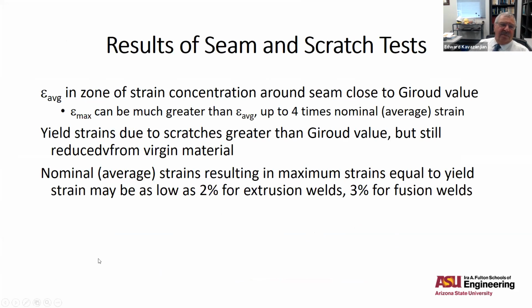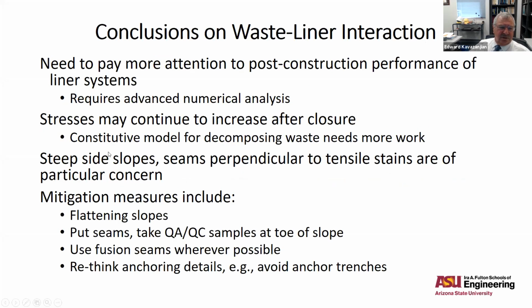So we concluded from these seam and scratch test results that the average strain in a zone of strain concentration around a seam is close to the Giroud value, but there's a maximum tensile strain that can be much greater than the average, up to four times the nominal or average tensile strain in the geomembrane. And, you know, geomembranes are pretty brittle materials. Once you start a tear, the entire geomembrane tends to unzip. The yield strain due to scratches is greater than the Giroud values, but still reduced from that of virgin material.